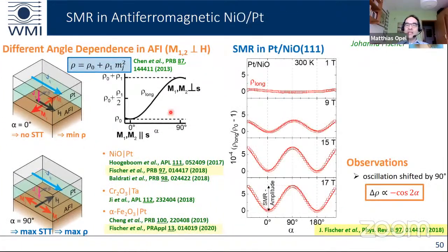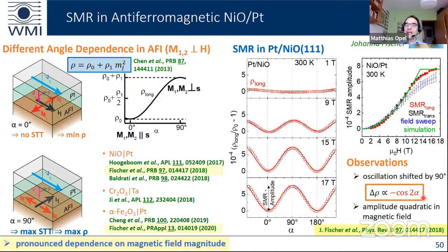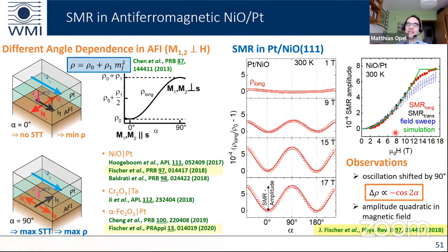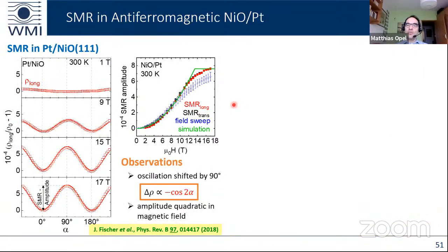This was theory. In our experiments, we applied magnetic fields from 1 to 17 Tesla, and we rotated the magnetic field in the field plane, and we find this oscillation now, which is proportional no longer to plus cosine 2 alpha, but to minus cosine 2 alpha, which is a shift of the oscillation by 90 degrees. We also analyzed the SMR amplitude as a function of the magnetic field, and we found that it increases quadratically in the magnetic field. We were able to explain this with the model assuming antiferromagnetic domains, but this goes beyond the scope of this talk.